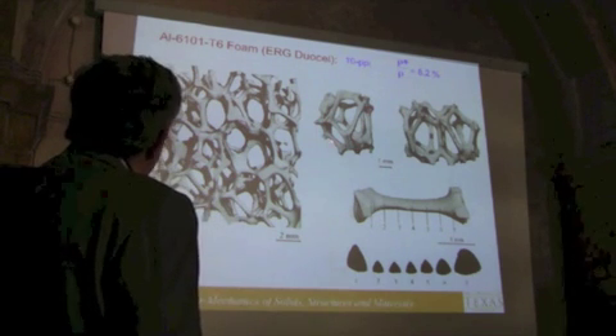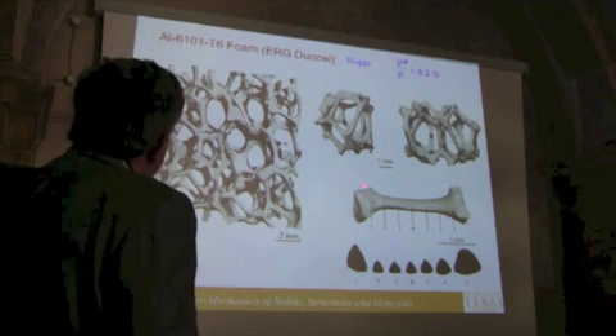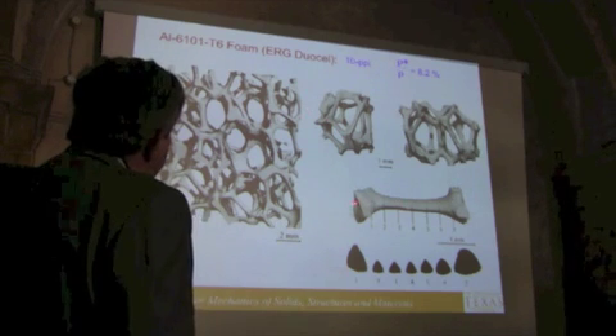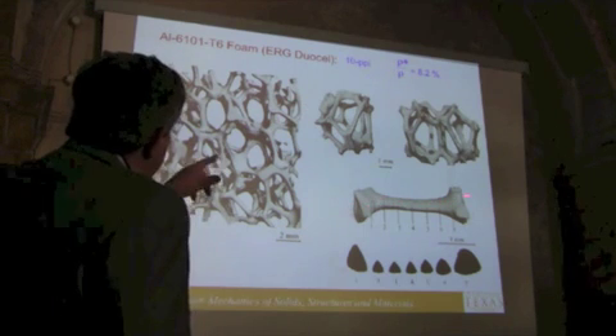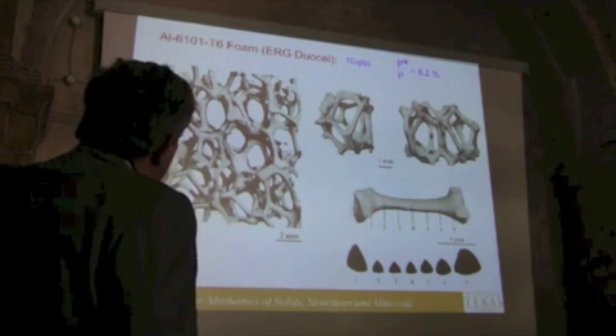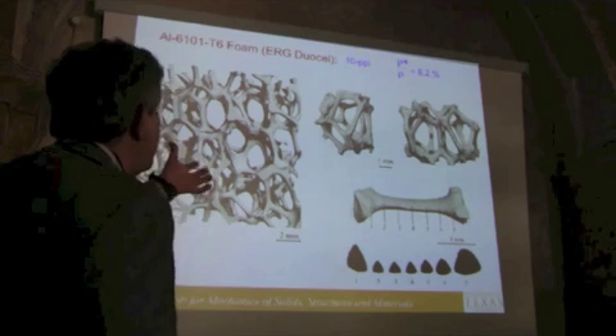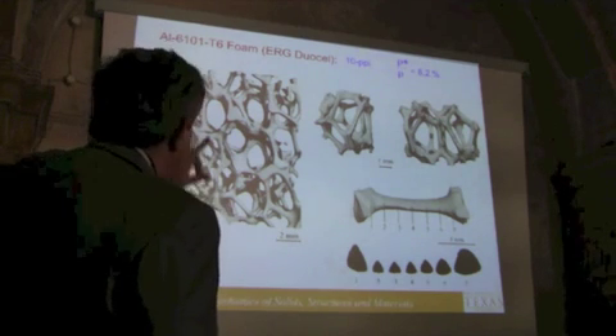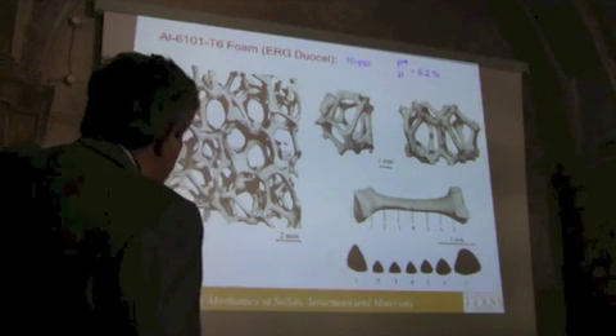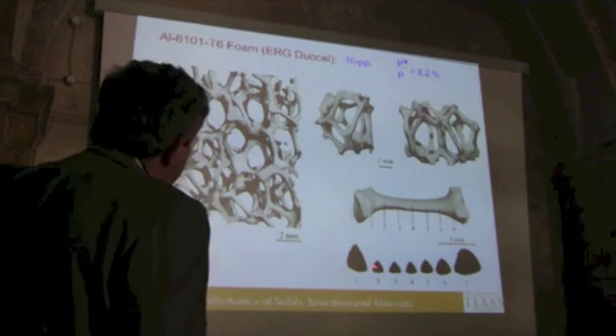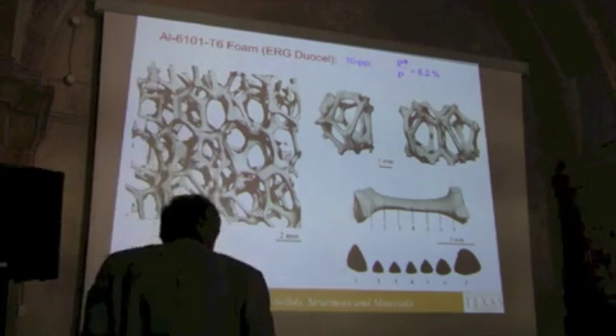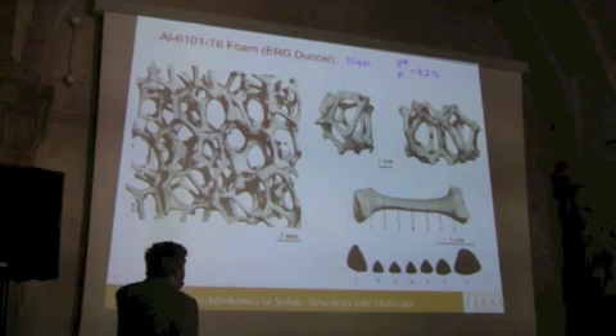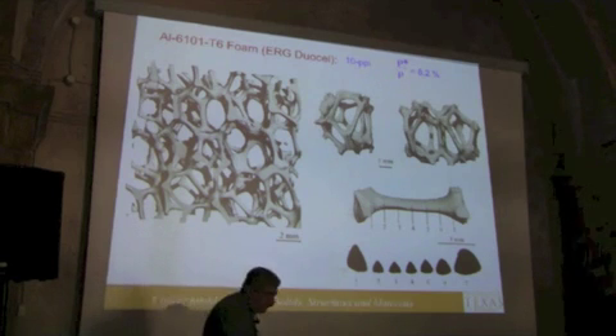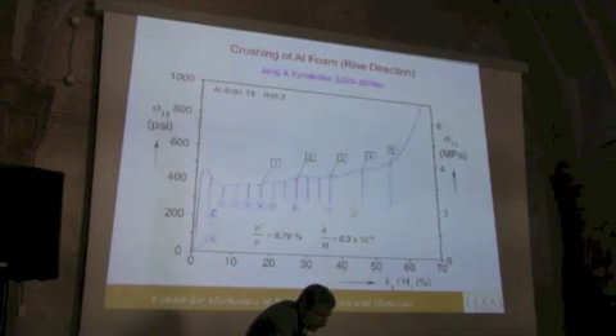I call these ligaments, not struts. The ligaments are like here, you see, again from X-ray tomography. That's what they look like. They look like dog bones. And the reason they look like this rather than plateau borders is because of the way this particular foam is manufactured. And you see that there is a variation in the cross-section. These are important ingredients if you want to do micromechanics, and that's really what we do.